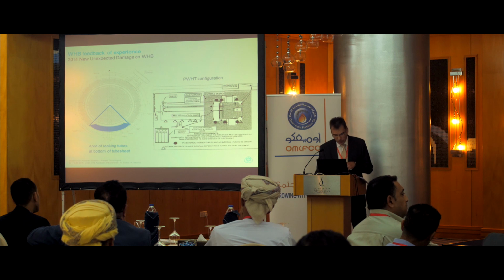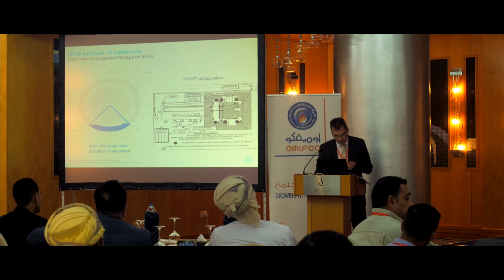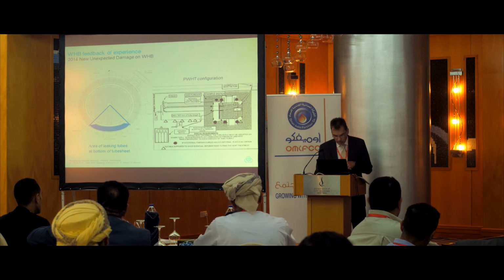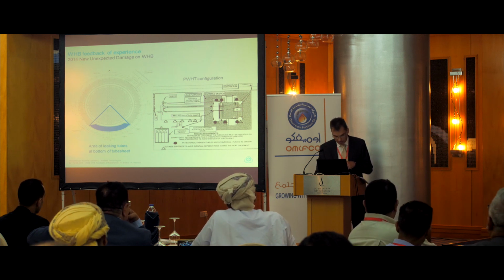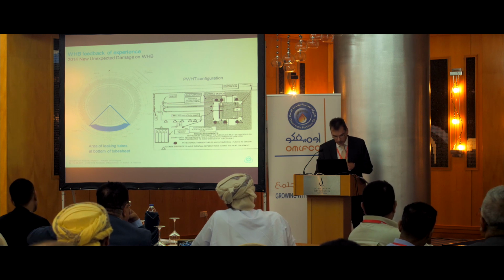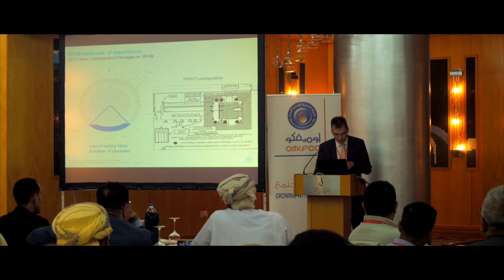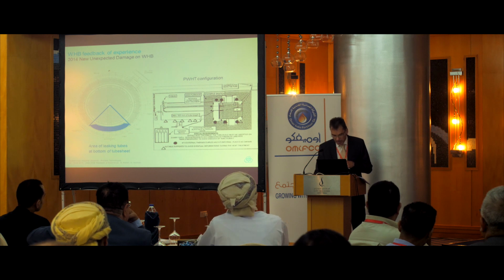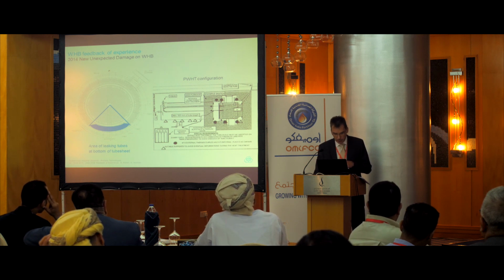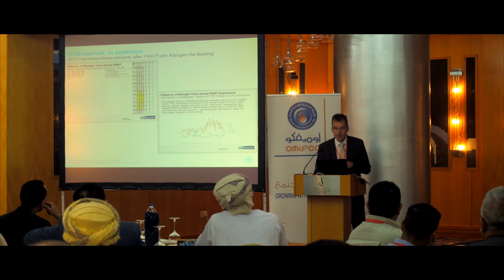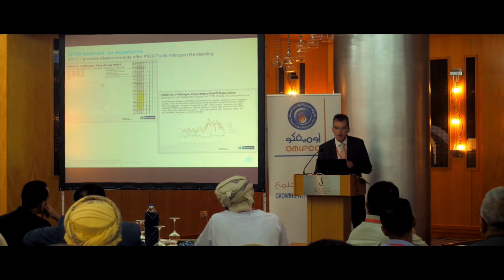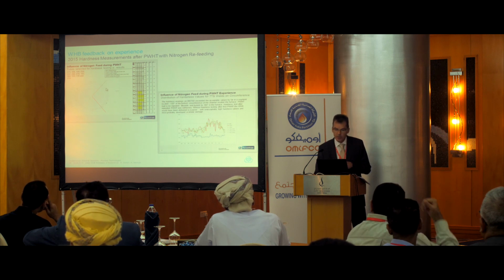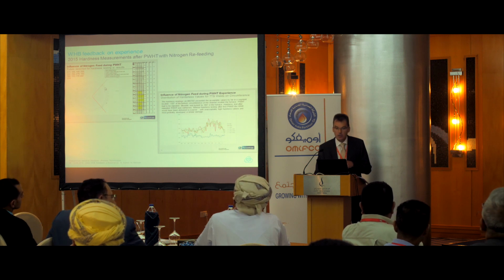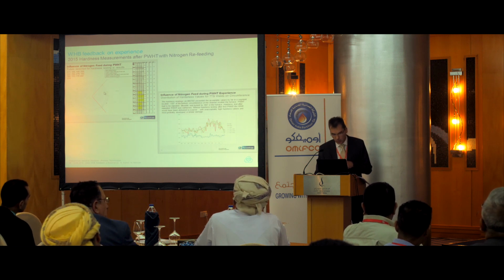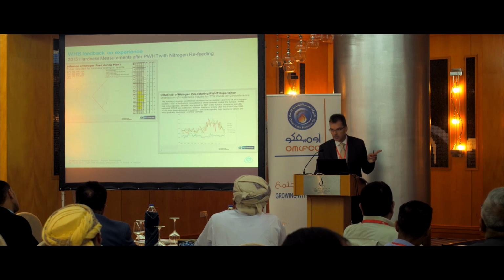But moreover, during the fabrication of new boilers in the plant in the USA, again during post-weld heat treatment, cracks had been noted on the seal weld. And again nitrogen was fed in. But this time we had the chance to check the fabrication and do hardness measurements on selected tubes. We have taken the results, and the results proved that in sectors of about 120 degrees, which you see here, which is again, if you turn it down, the location of how the waste heat boiler was heat treated, we have very high hardness values, which of course proves that this is the reason that the cracks occurred in the other waste heat boiler during operation.